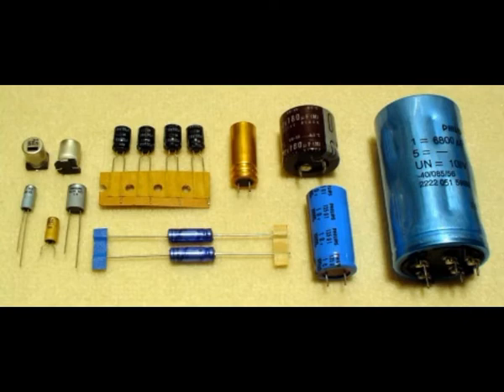The reciprocal value of FIT is the MTBF, the mean time between failures. The standard operating conditions for the failure rate FIT are 40 degrees Celsius and 0.5 UR. For other conditions of applied voltage, current load, temperature, capacitance value, circuit resistance for tantalum capacitors, mechanical influences and humidity, the FIT figure can be recalculated with acceleration factors standardized for industrial or military contexts. The higher the temperature and the applied voltage, the higher the failure rate.